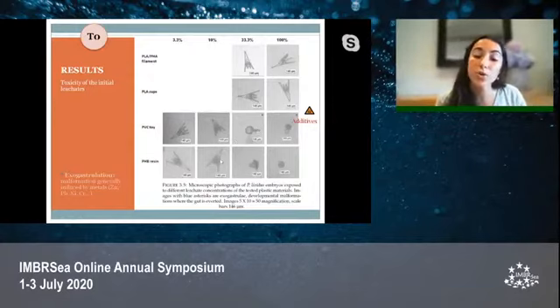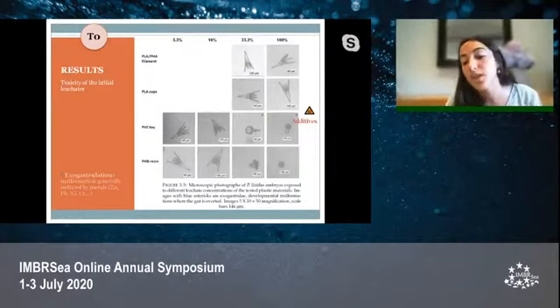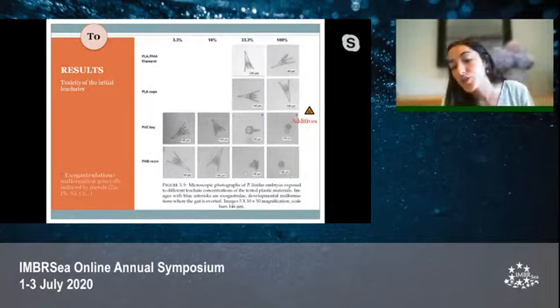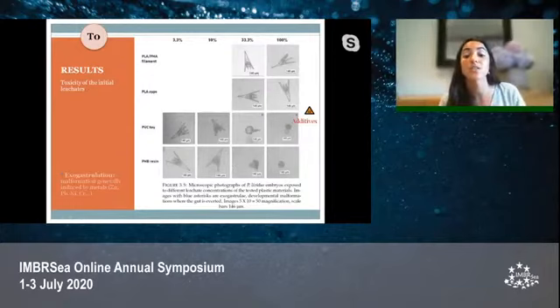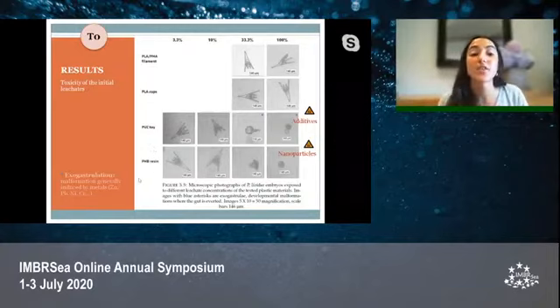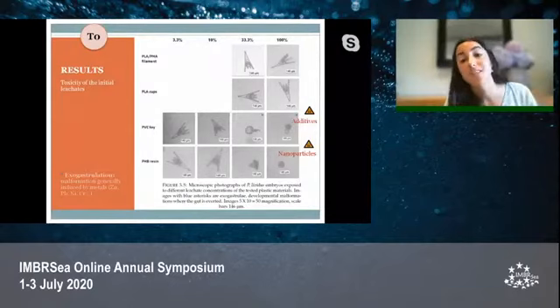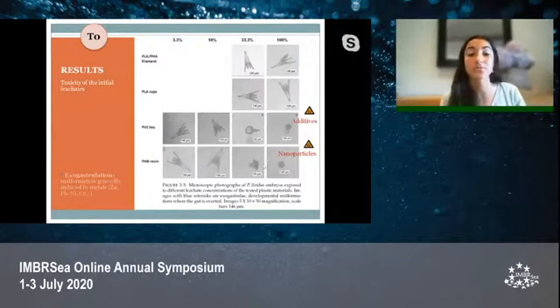Then for PHB resin, although in theory it's a non-toxic and biocompatible polymer, you can see here that it shows some toxicity. I suggest that this is related to the size of the fragments, because actually the size of the resin fragments was on the nanoscale. And it's known that nanoparticles can alter different physiological pathways of the sea urchin, and they can even increase the production of reactive oxygen species, therefore affecting their membranes and subsequently causing developmental block.